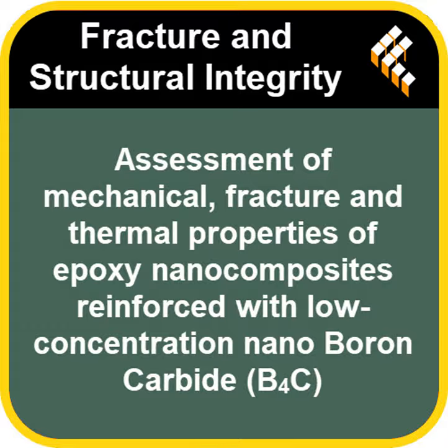Okay, but here's a question. If 0.3% was the peak, why did adding just a little bit more, up to 0.4%, actually cause the tensile strength to drop? It went down by about 17% from that peak. Ah, yes. That's where the downside of nanoparticles comes into play, agglomeration. Even with that intense ultrasonication, once you get to a certain concentration, in this case 0.4%, the nanoparticles just naturally want to clump together. And these clumps, these clusters, they act like tiny defects within the material. They become stress concentration points, basically weak spots where failure starts easily when you pull on the material.